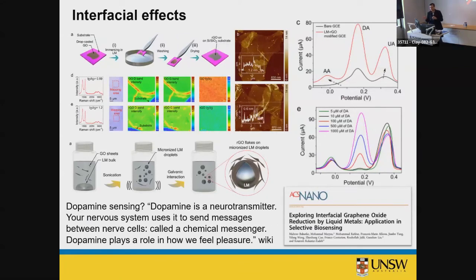Interfacial effect of liquid metal is very interesting. For instance, if you put graphene oxide on a substrate and dip it into liquid metal, naturally it goes from graphene oxide to reduced graphene oxide very evenly on the surface. Here we showed the studies, and we wanted to make some devices. Sonicated liquid metal together with graphene oxide on the surface becomes reduced graphene oxide, highly conductive. It becomes a very interesting material with interesting electrochemical properties.